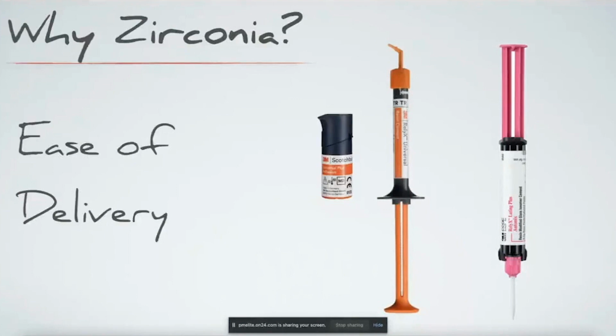So I could skip the bonding step, put that cement in the restoration, seat the crown, cure it. My bond strength has gone up. But if I really want to make my bond strength go higher, if I'm like, man, I don't know if I have quite enough mechanical retention on that prep, I simply can combine these two. So I could apply the Universal Plus adhesive to the preparation, blow it thin.